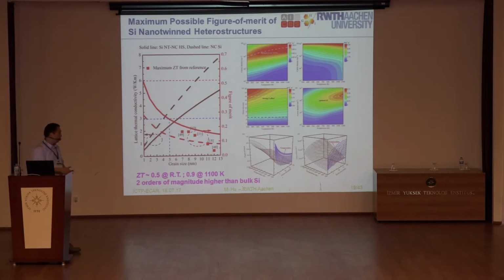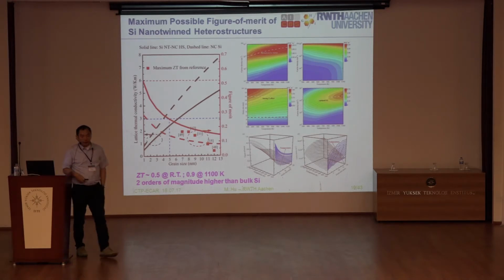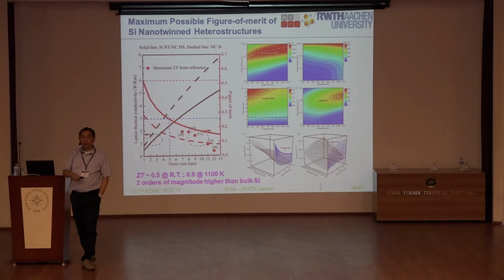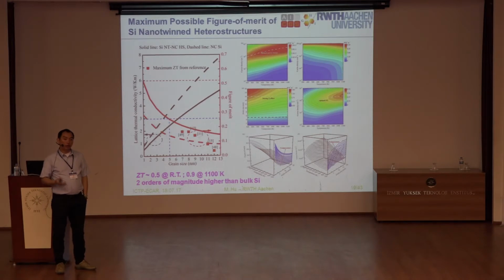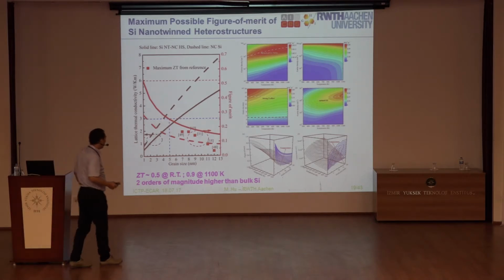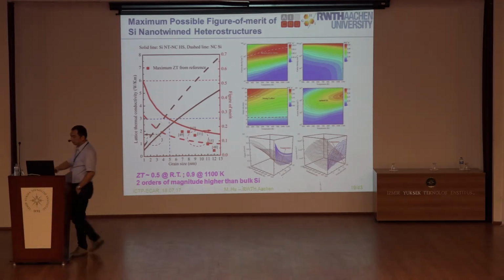So recently with the same idea, we are working on lead telluride, PbTe, which is a very common, very widely used, very excellent thermoelectric material. With the same idea, we found a significant enhancement in the ZT coefficient.